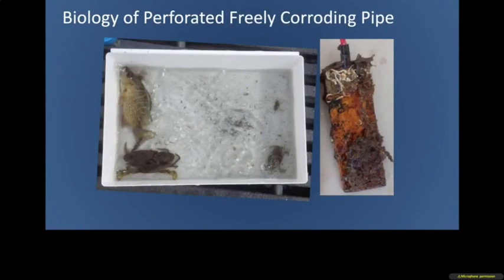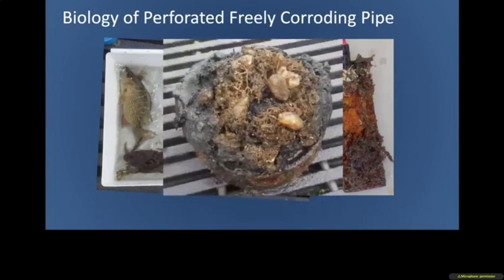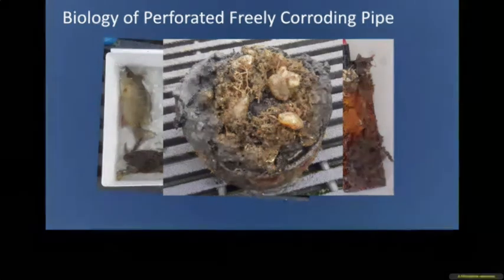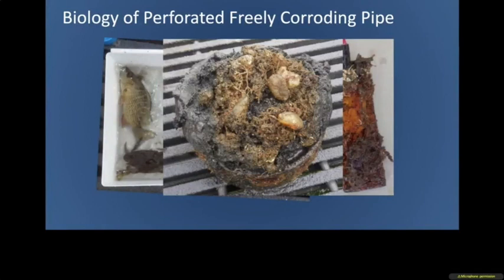So what was living in these pipes? When we removed the perforated pipe from the water, we collected everything that was inhabiting it in a little tray. And there were a few things living in the perforated pipe. But the other thing we noted was that because the biofouling continued to be exfoliated, it actually formed an organic, kind of unpleasant mud at the bottom of the pipe. So unprotected perforated pipes, probably not too good an idea.